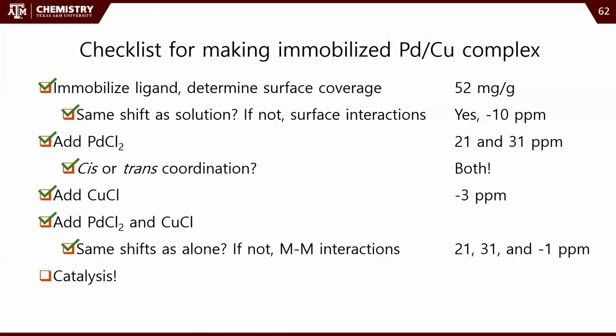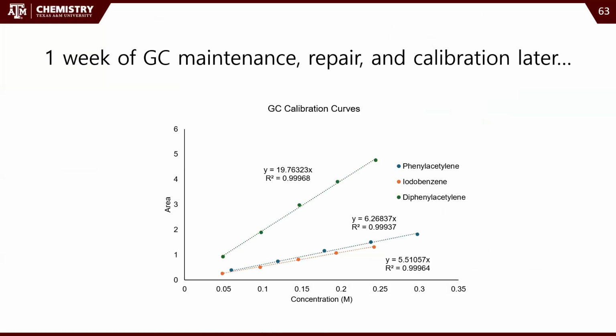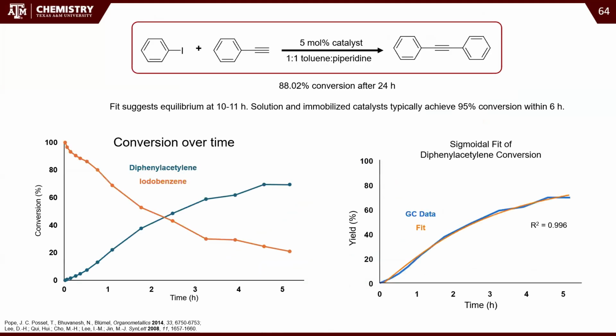So let's just move on and see if we can do catalysis. If we're making the complex that we think we are, and it works the way we're hoping, the catalysis should be significantly better than what we see in the literature. So first I fixed the GC and calibrated it and got nice curves for all of my starting materials and my product. And then I did catalysis and we turned over. It works. We got product, starting material dropped down. I was able to fit the curve and get pretty good agreement.